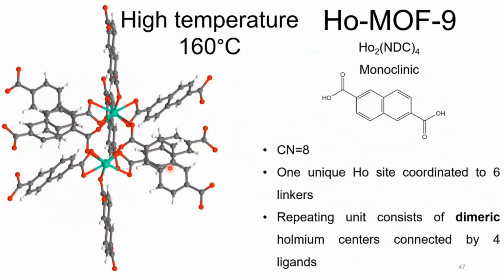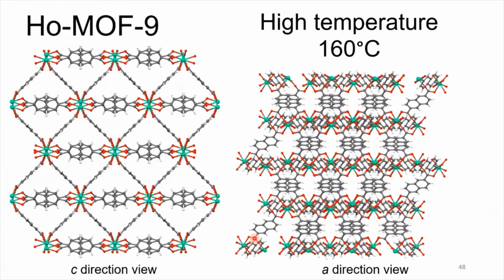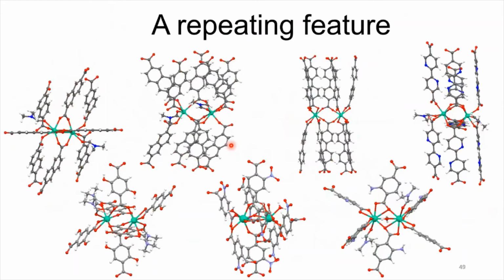And this is interesting because we actually don't see any solvent coordinated to the metals. We still have a dimeric holmium cluster in the repeating unit, but no solvent in it. And you can see we still see some bending of that linker, but no solvent in there, which is very interesting, very promising. So these are some of the structures that we were looking at. As I mentioned before, you can add nitro groups or hydroxy groups or amino groups to these to open up your structures. I just showed some of the structures that we have done. We have dozens that we have prepared and characterized.